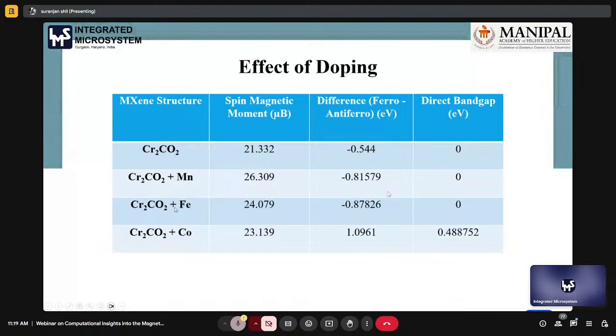Again, if we dope with iron, we got an increase compared to the undoped. It was 21.3, here it's 24. But if we dope with cobalt, again it increases the magnetic moment. But the problem here is that in cobalt dope, we got an anti-ferromagnetic configuration. That means the anti-parallel spin configuration is the stable one. But fortunately, we got that it is semiconducting but anti-ferromagnetic.